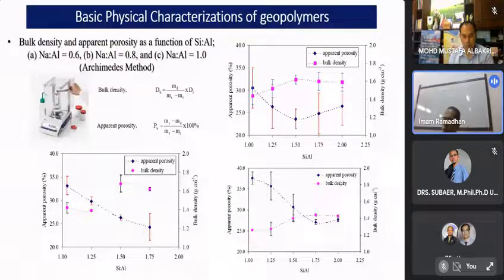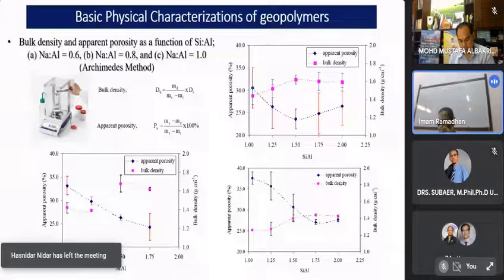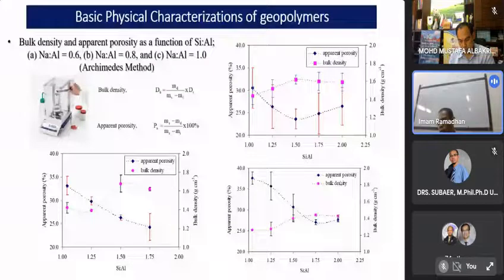It's actually impossible to stop the development of pores inside the bulk geopolymer, because we produce geopolymer by using water, by using the alkaline solution, and then we heat it up to around 70 degrees or 75 degrees or even sometimes 80 degrees. So the water will eventually evaporate to the surface of the geopolymer and leave behind pores, of course, or water trapped inside the geopolymer. So that becomes a void in our geopolymer. But that's not always bad, because sometimes we need the porosity of geopolymer for other functions. So it depends on the purpose of our research.